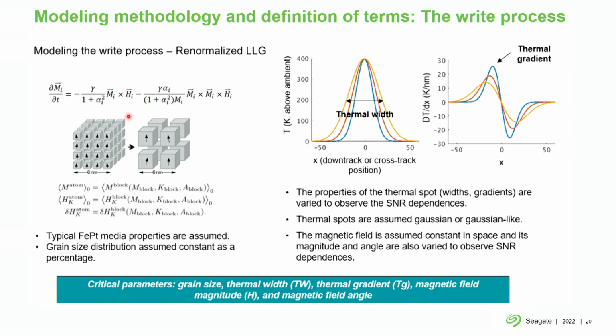But with HAMR, we can't do that anymore because we're operating at very high temperatures, close to the Curie temperature, which is the temperature at which magnetic materials lose their magnetization. So nearby atomic moments are actually randomized. They're not all pointing in the same way. But if I wanted to model an entire data sequence with hundreds of bits, I really can't do that using an atomistic simulation because it would be billions of atoms, so it would take too long.